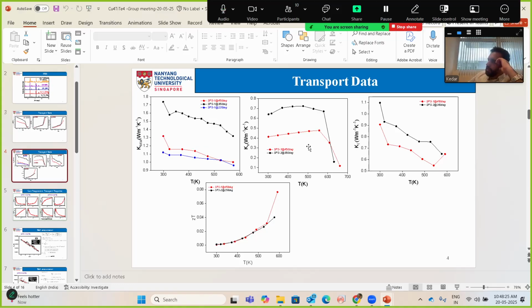The good news is your lattice thermal conductivity is already pretty low. So for a new compound, if you're able to dedope, this is the original idea. Let's get there later. I don't think you need to rush. Let's figure out what's happening in the phase transitions. You're still metallic. You have a lot of room. If you're able to dedope very nicely, then definitely your power factor will go up by easily an order of magnitude. Then you'll be in some useful range, right? A ZT of one with no additional modules is a very good paper. So it's quite promising.